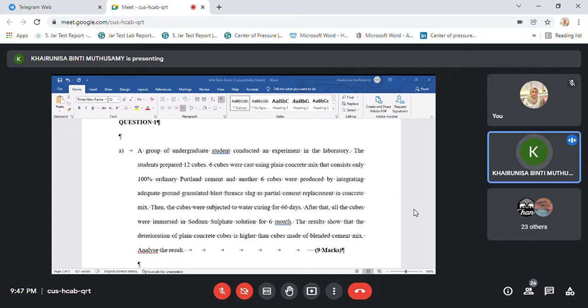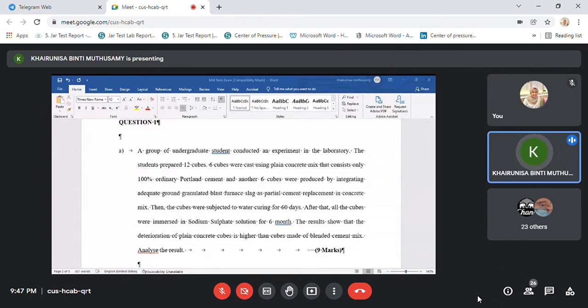Okay. Then you need to compare with the performance of normal concrete. Okay, you need to mention what are the reactions present in the concrete containing slag, which is the hydration and pozzolanic reaction. It has two reactions that contribute to the formation of larger quantity of CSH gel. On the other hand, the control concrete only relies on the formation of CSH gel through the hydration process. So when we compare which one is more compact in the internal structure, it is definitely the slag. Itu satu.